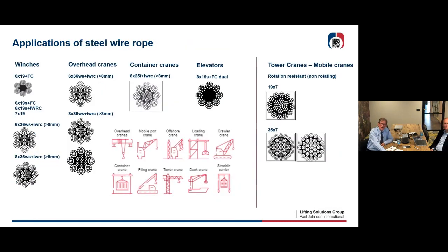Applications of steel wire rope. Well, I just put on some examples. Winches: you can use 6-strand ropes or 8-strand ropes, depending on the strength you need, the flexibility you need. Overhead cranes: you have 6-stranded, or if you want a rope which lasts longer, rounder, you can have 8-strand ropes like presented there. For container cranes, we normally advise 8 times 25 with filler. You can get it from 8 millimeter and bigger diameters.